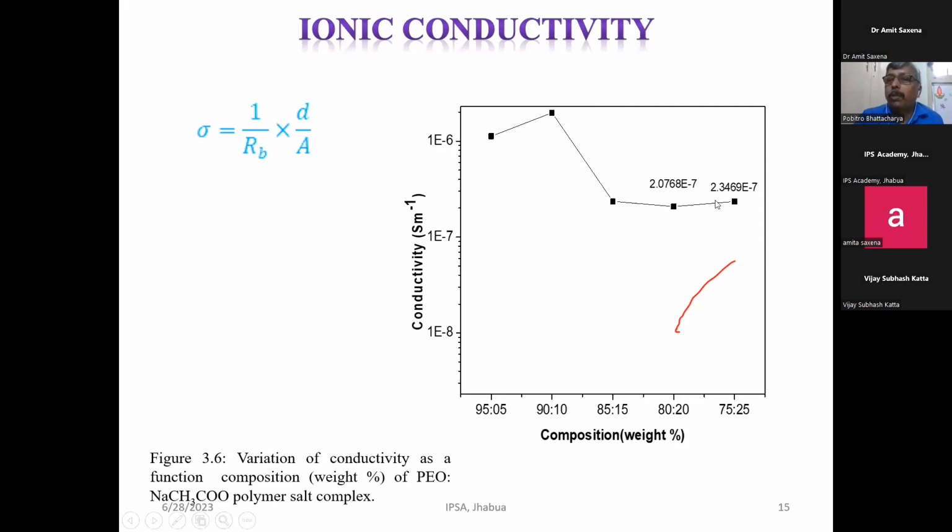One may continue with low conductivity or get a slight increase in the conductivity. That is due to either the redissociation of those clouds or the movement of those clouds throughout due to the increase in mobility. The amorphosity increases and the mobility therefore increases due to that. So that depends upon what type of salt, what is the nature of the matrix, but broadly this is the common feature.